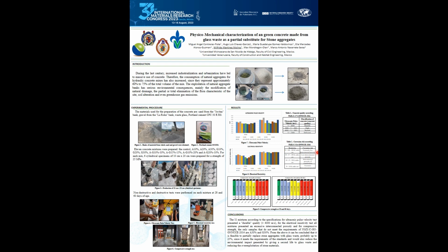From the above, it can be concluded that it's feasible to partially replace stone aggregates with glass waste, probably up to 25%, since it meets the requirements of the standards and would also reduce the environmental impact generated by giving a second life to glass waste and reducing the overexploitation of stone materials.